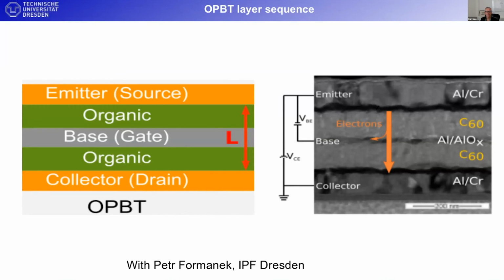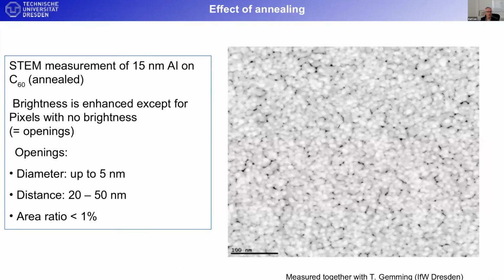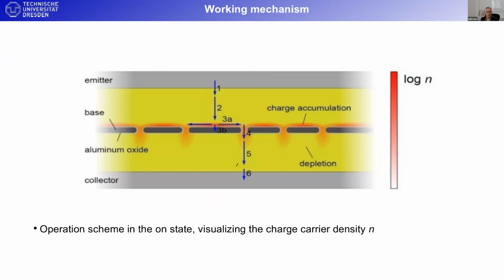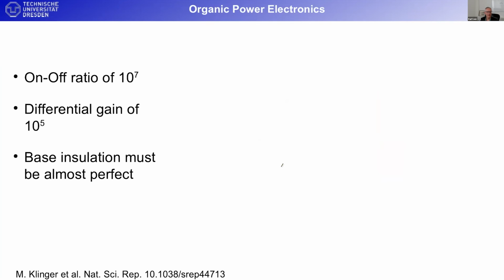Well, you have here a C60 layer where you inject electrons. Then you have a base contact where you apply the control voltage and you control the current to the collector. To make this work, actually, you need to have some transparency in the base. This means this base has to have some holes, which is achieved by putting it under air where it forms little aluminum oxide covered crystals with some holes in between. You can see that in electron microscopy that there are small holes and the carriers go through these holes, and that works actually very efficiently. So they are pulled down by the field, then they diffuse to an opening, and then they are pulled to the collector down here.